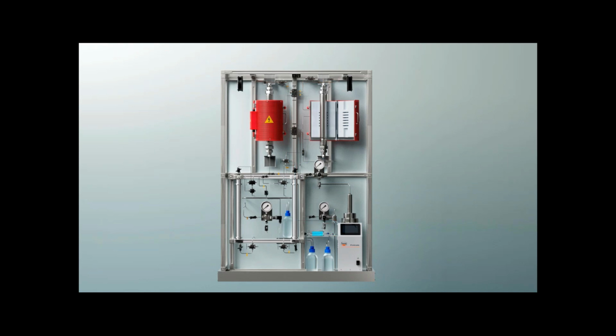So this setup allows us to mix a fluid in between the two pressure vessels. And if you remember correctly, the first one is the preheater for reinjection simulations, and that depolymerizes the silica. But if we want to test an anti-scalant compound, we don't want to have to heat that compound up to 250 degrees in the preheater. We want to put that in there without preheating. So the second fluid can contain the anti-scalant and go in between the two, and it's actually not heated. And then the two mixtures can go into the reactor where the rock is, and we can test anti-scalants, for example.